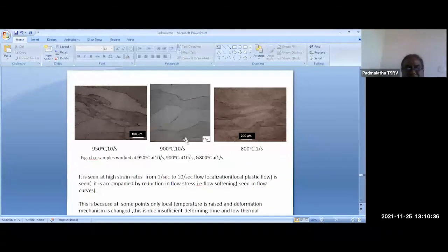But at higher strain rates, we can see some flow localization. See, small new grains are formed, but they are formed locally. Here also you can see the new grains are formed, but they are formed locally. Not the entire structure is of small recrystallized grains, but these small recrystallized grains occur only at particular locations. Why this has happened is because we are working the material at a higher strain rate.